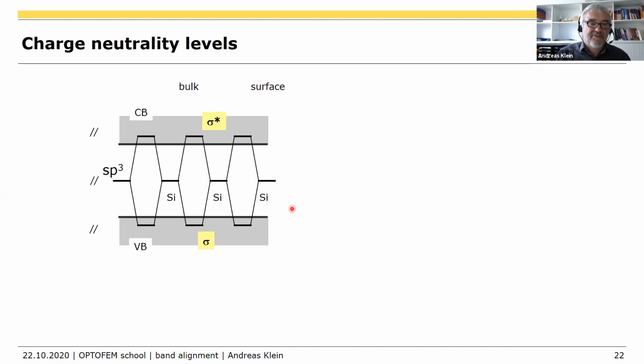Consider silicon, it's a tetrahedrally bonded semiconductor. So we have a tetrahedral coordination, we have sp3 hybrids. These sp3 hybrids form bonding orbitals when they overlap between the silicon atoms, and anti-bonding orbitals. And the bonding ones are the occupied ones, they form the valence band, and the unoccupied ones, they form the conduction band. If you go to a surface, your silicon has no bonding partner. So that means you have your sp3 orbital, a dangling bond, and the energy is approximately that of the sp3 orbital. And this sp3 orbital is between the occupied and the unoccupied state. So it gives us an electronic state in the band gap.